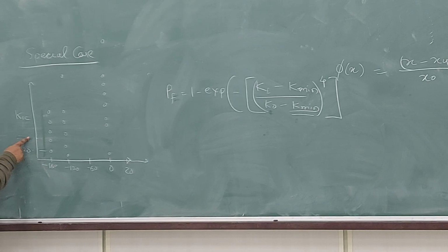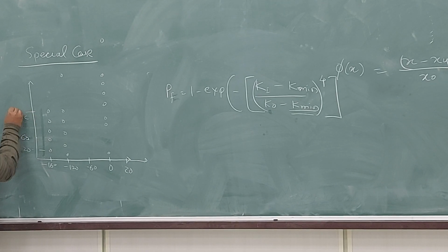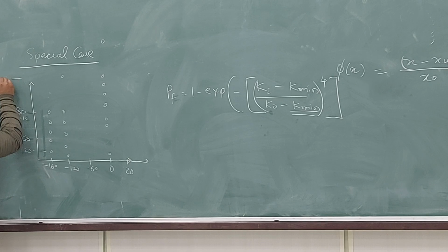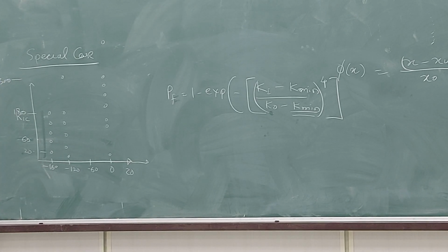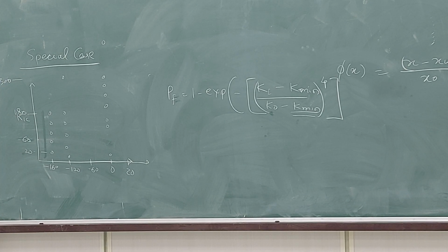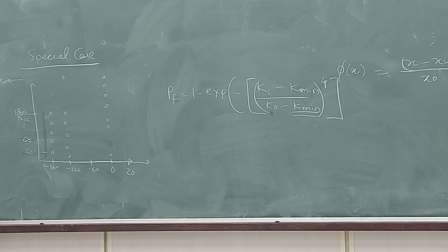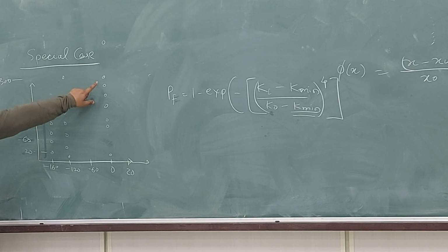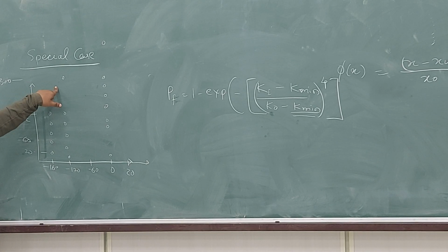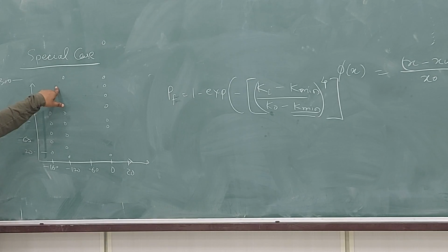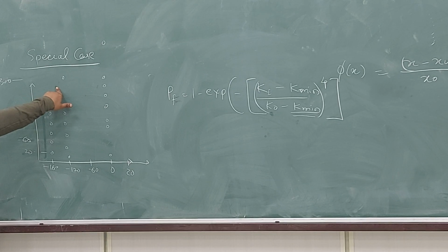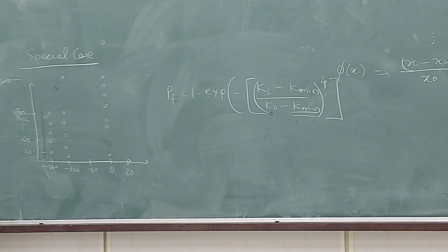It's 20, it's 60, it's 180, this is 300. Okay, so the fracture toughness which you think is coming at 0 degree, you are also getting at minus 120 degree for one sample. Why is that happening?